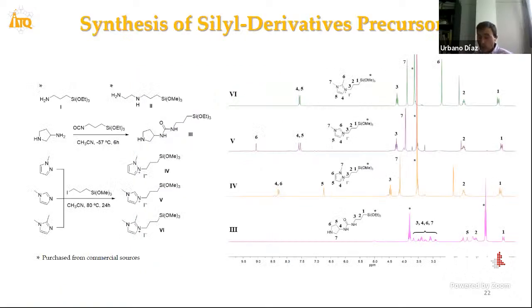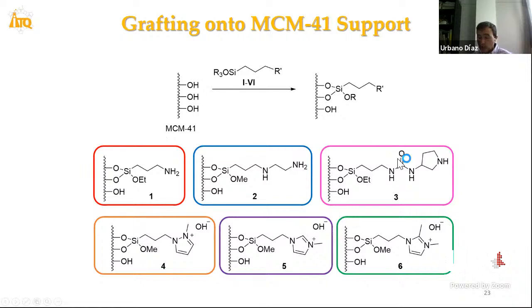The first step was, as introduced in the first slide, the preparation of a suitable organic-inorganic precursor containing this type of base groups with terminal siloxane groups. The characterization from NMR was successful to confirm the presence of these base groups. This precursor was used in grafting processes using MCM41 support to incorporate this type of base groups in the surface